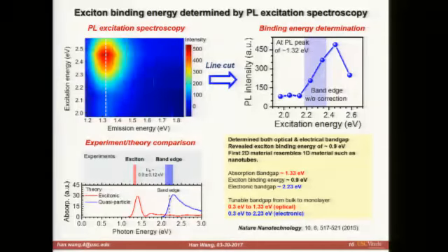So when we go from bulk black phosphorus to a single layer, the optical band gap can go from 0.3 eV all the way to 1.33 eV. This highlights the potential of the material, and it's always a direct band gap, so it highlights the potential for infrared optoelectronics applications.